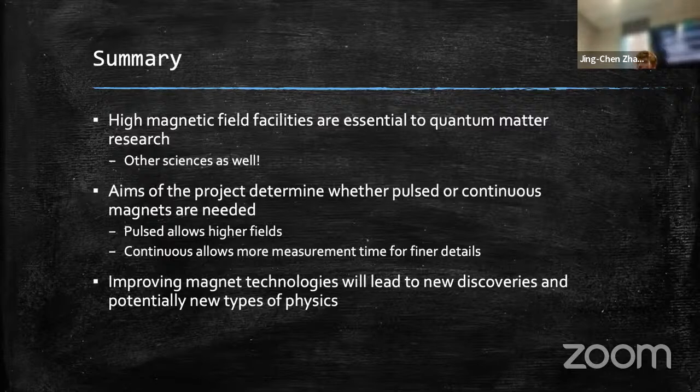Then let's be more specific. Why do we need to go to such high magnetic fields? Is there anything new that shows up in physical models at high magnetic fields? Well, normally you wouldn't expect superconductivity to reemerge at 40 Tesla, and here you just measured a sample and it did. Because it does, you might have a more complicated superconducting pairing, or some other interaction happening that you wouldn't expect in the system. I see. So you can say this theory maybe doesn't support this behavior at higher fields, so something else is going on.